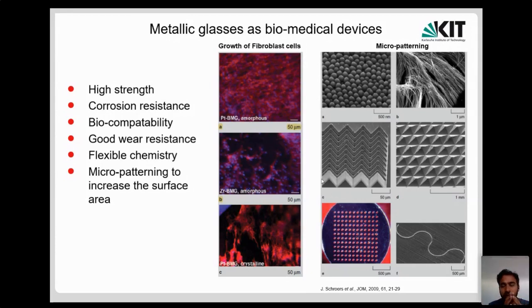But the most important one, as far as I have understood, is that when you have a rough surface, obviously you have more surface area, so the bacteria or the cells can come and sit on it and grow on the surface. And for that, you need to increase the surface area. And this can be done with glasses very easily, because I told you that with high temperature deformation, you can always get the glass to flow like a semi-viscous liquid. So you can take a piece of glass, take it to high temperature, and then take a stamp like this. Let's say you take this stamp where you have this kind of very rough surface. You take a mold of the stamp and you stamp it, and you can get such a structure in the sample. You generate such structures